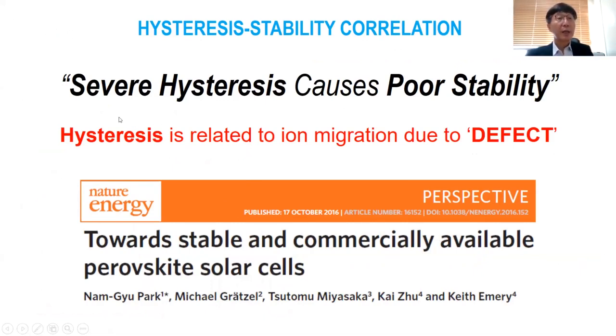In addition, if you have very severe hysteresis, then you cannot guarantee the stability of the perovskite solar cell, because the hysteresis is closely related to the defect. So if you create a defect, then you cannot guarantee the stability, because a defect is a kind of seed for propagating the instability.